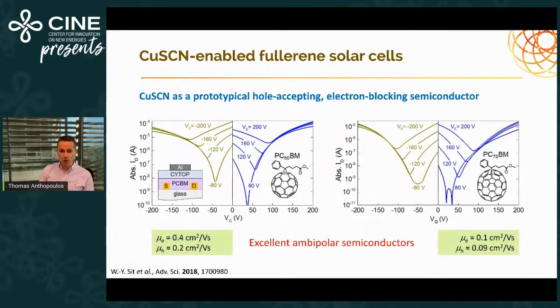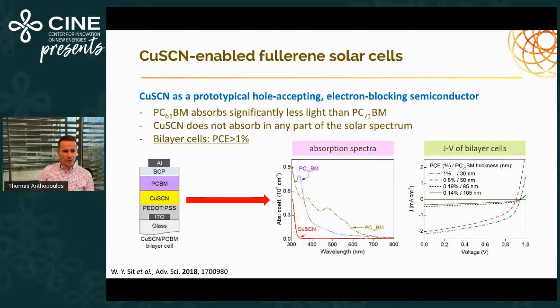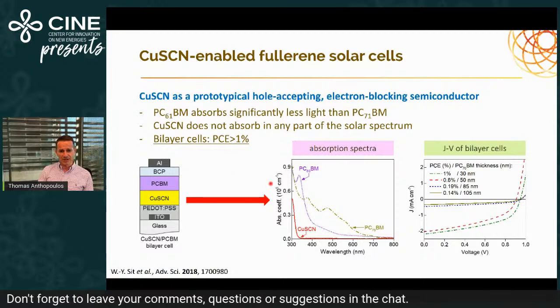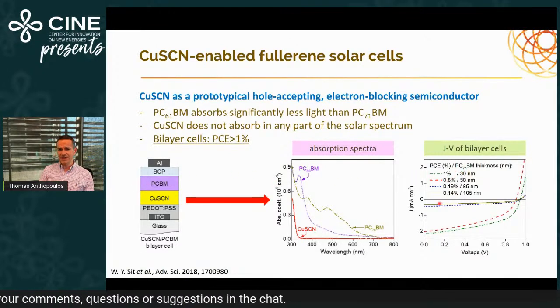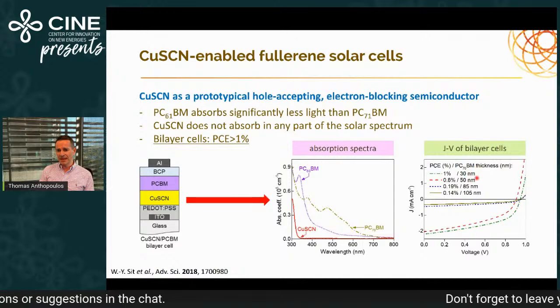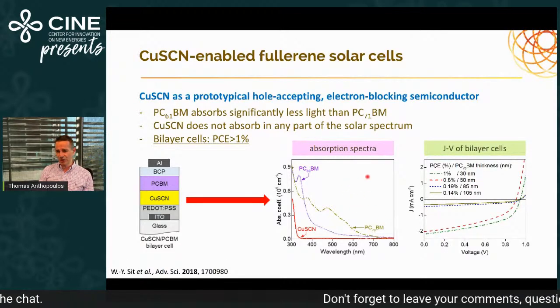So we went ahead and we used fullerenes because the fullerene derivatives we know are perfectly symmetric in electron and hole transport. They exhibit essentially the same hole and electron mobilities, and therefore are materials that can photogenerate: you can photoexcite them, create these charges, and try to separate them. So what we've done, we took copper thiocyanate, we deposited on top a pristine layer of PCBM and created bilayer devices. And depending on the thickness of that PCBM layer, we could get up to 1% efficient devices.